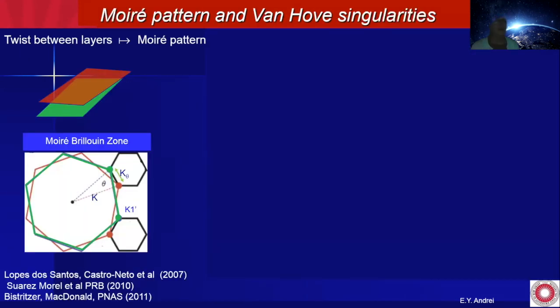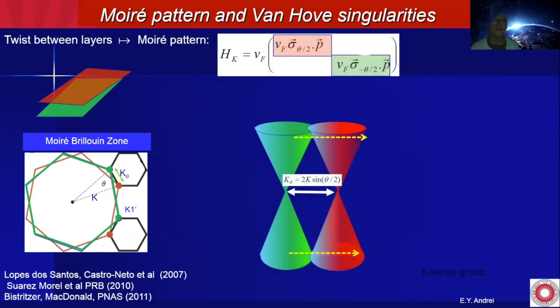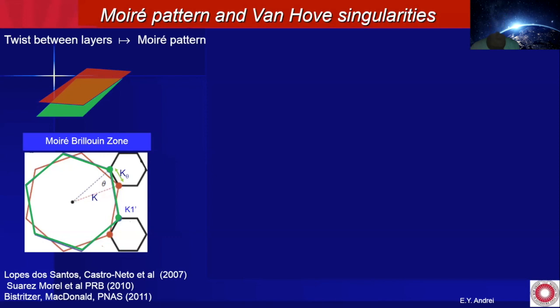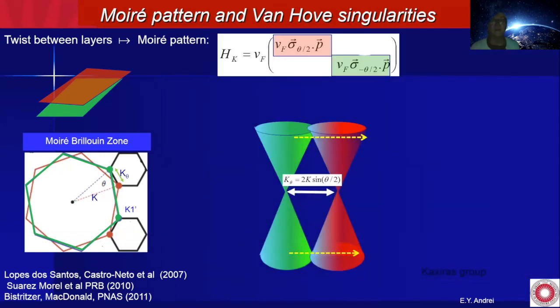So let's take this red layer on top of the green layer, and that gives you a corresponding stacking of the Moiré-Brillouin zones. You see that the K value of the green layer is displaced from the K value of the red layer by a wave vector which depends on the twist angle. The larger the twist angle, the further apart they are. So this little region here is our mini Brillouin zone. We've cut down our Brillouin zone into small pieces, and this is where we're going to be looking for our flat bands. If I'm looking at the Dirac cones, the green and the red, you see that they meet here at an energy that depends on the twist angle.